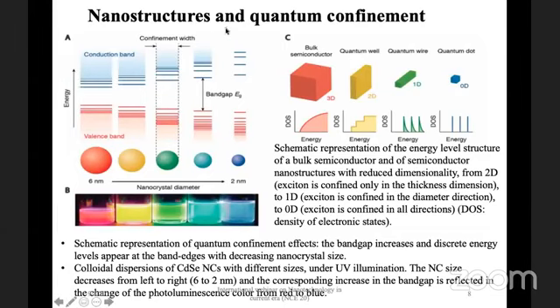Now, what happens is when we have nanostructures, the quantum confinement effect comes into play. On the left side, we have cadmium selenide nanocrystals. The size changes from 6 nanometers to 2 nanometers. And you can look at that at 6 nanometers, the band gap is small. But as we decrease the size of the nanoparticles, the color shows which wavelength it is going to absorb or emit when we shine light on it. So we go from red to blue to the ultraviolet as we decrease the size.